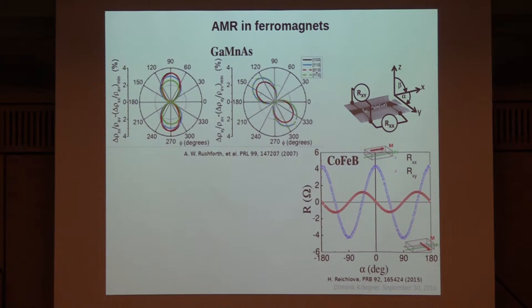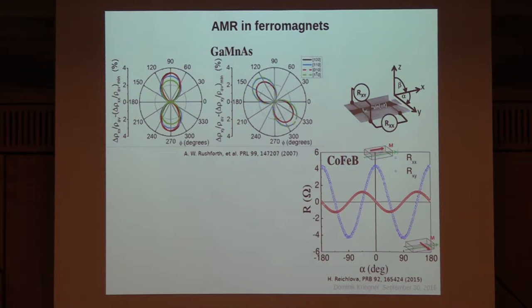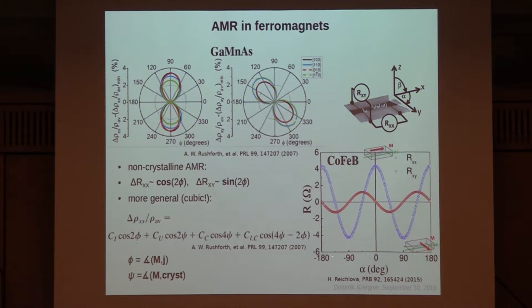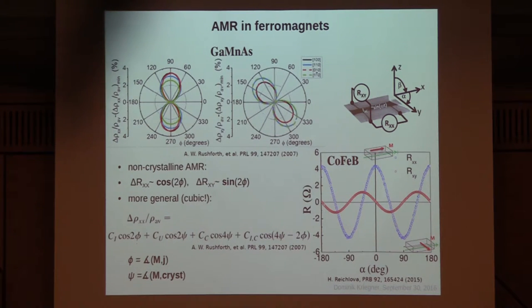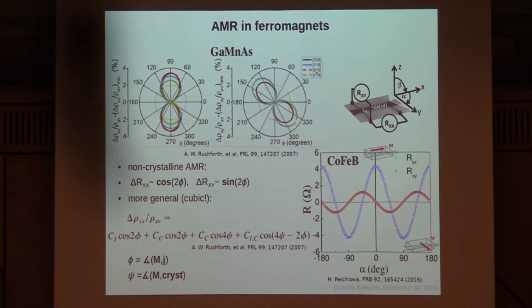AMR — anisotropic magnetoresistance — is a harmonic dependence of the resistance on the magnetization direction versus the current. It's typically measured by applying a magnetic field in the saturation regime to a ferromagnet, for example in thin films, and rotating this field in various directions with respect to the current direction. You detect this harmonic variation: a cosine of two times the angle between magnetization and current. When detected via the transversal contacts of a Hall bar, you get a sine-like trace from the same effect.